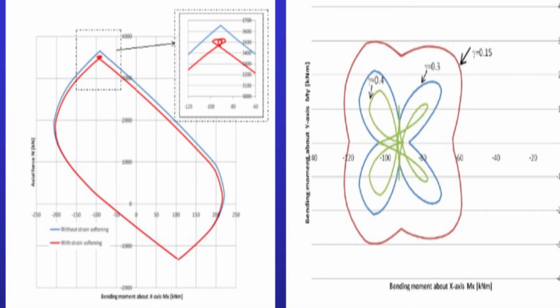This cross-section has been analyzed trying to determine the moment curvature diagrams, and we observed that when the strain softening effect of the concrete in compression is taken into account, the moment curvature develops snapback. The response is very hard to determine using the traditional methods that control analysis only in deformations. Our procedures use the arc length method. The results are controlled in deformations and loads simultaneously.